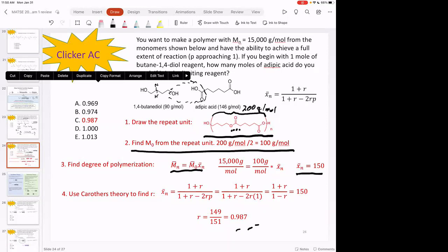Yes. So when you divide by two, don't we do that if you're combining monomers with one polymer? Or if there's two? It is the number of monomers in the repeat unit. That's the definition. So for all the examples we've done for step growth, where it's RA2 plus RB2, it's two monomers going in, but it doesn't have to be two monomers, right? So if there was three, you divide by three. Sure, we haven't done any examples of that, but yeah, it'd be three. And in addition polymers, it's one, right? So we just divide by one.